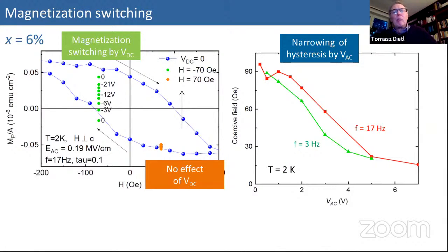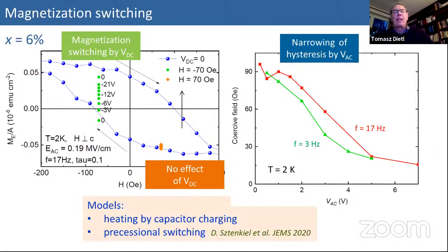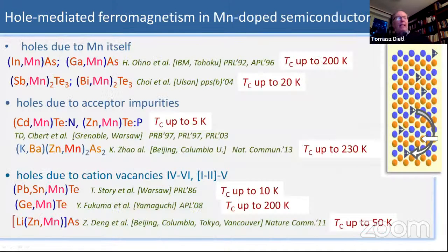And how to explain it? One of the explanations would be that we have just heating, because what we do is charge capacitors, and heating could just bring our system to thermal equilibrium when we cool down afterwards. So one of the possibilities here is heating by capacitor charging. But actually, in one week, on Tuesday, during the jam session, D. Sztenkiel will try to convince you that we see precessional switching. That it's not heating, but we observe precessional switching induced by this additional trigonal field, which we introduce here.